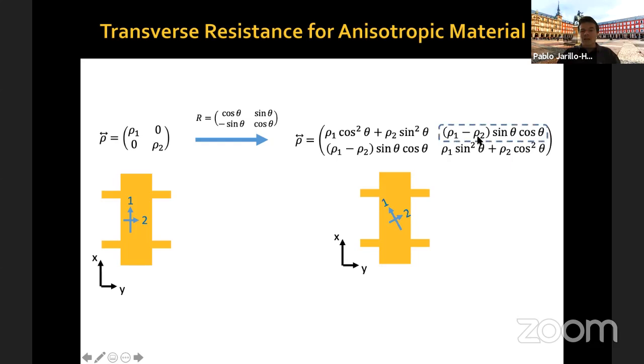And as long as you don't have sine of 2 theta, this rotation angle, equal to zero, you will measure a finite rho xy resistivity if the system is anisotropic. And in fact, that measurement is giving you a sense of what is the anisotropy which is present in your system. So in our magic angle graphene devices, we don't know what the crystallographic orientations are. So we in general shape our Hall bar devices along some direction, which is, in general, arbitrary with respect to this anisotropy axis.